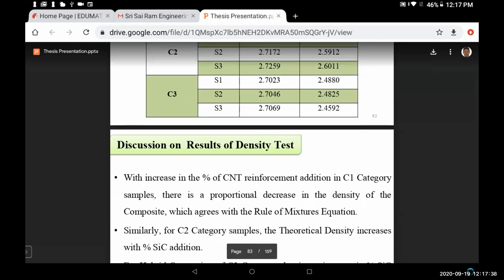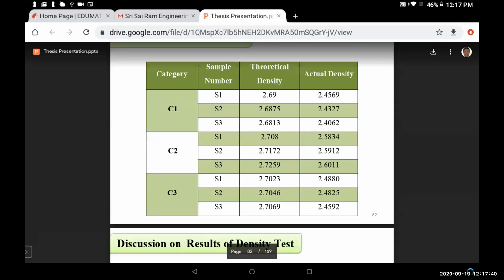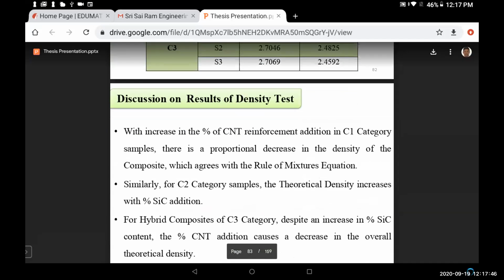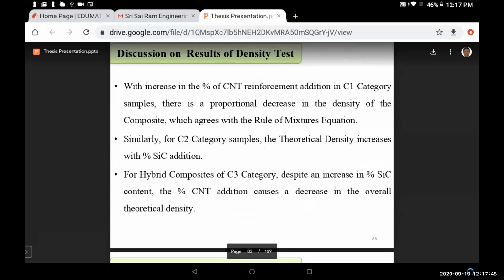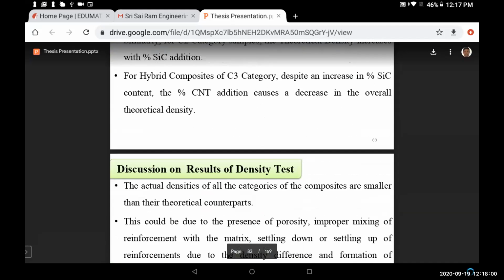In the density test, you will see the density of C2 is higher than C1 and C3. The theoretical density increases with the percentage of silicon carbide. Since C2 contains silicon carbide alone along with the aluminum, the density of the silicon carbide composite is higher than the other two.